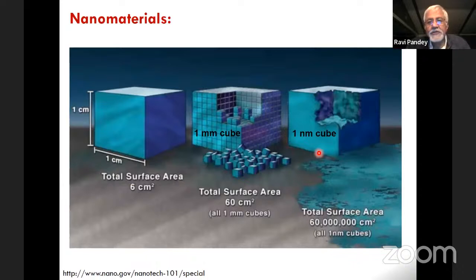So what is special about nanomaterials? You may have seen this slide again, but it gives you the power conceptually. If you look at a cube of a centimeter by a centimeter, the surface area is going to be about 6 square centimeters, because you have 4 plus 2, up and down, 6 surfaces. If you go further down, instead of a centimeter cube, we pick a millimeter cube. We subdivide it, and the surface area has gone up at least 10 times. Going from centimeter to millimeter, the surface area increased by 10 times, from 6 square centimeters to now 60 square centimeters.